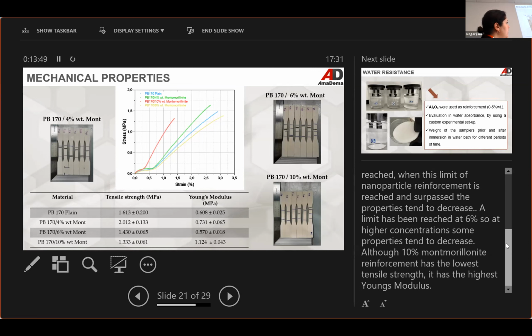As you can see here, the 10% montmorillonite has a weaker response, and the 4% actually demonstrates the best tensile strength. What was really surprising is that the 10% montmorillonite, even though it has quite low tensile strength, demonstrates a higher Young's modulus.